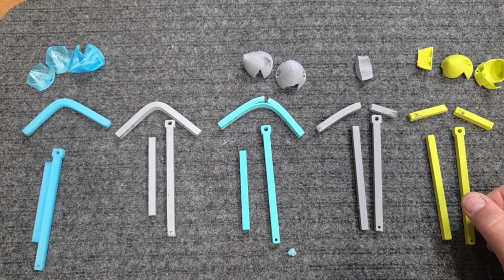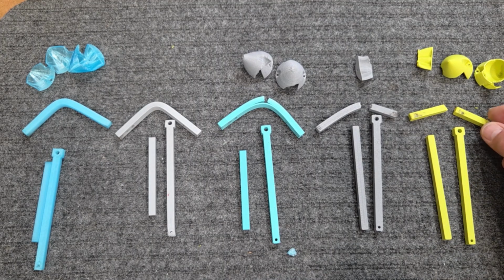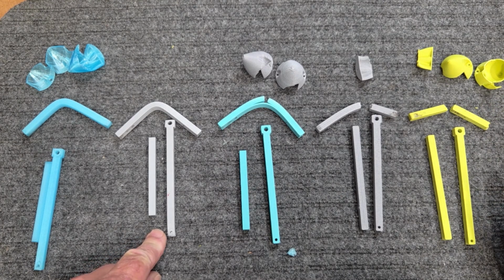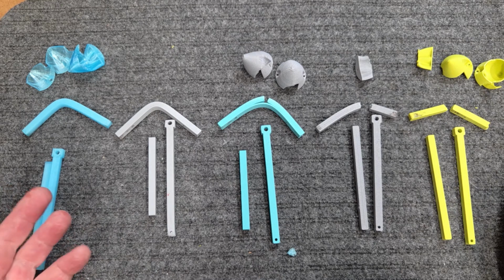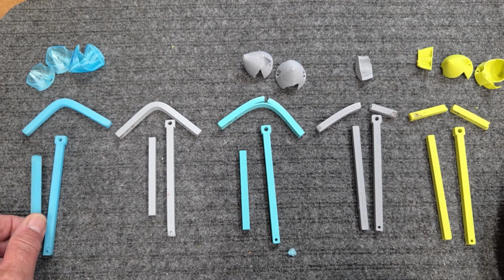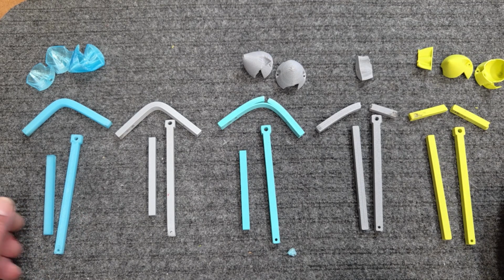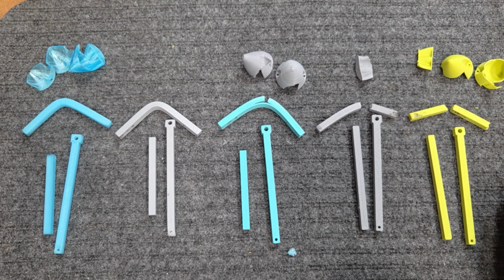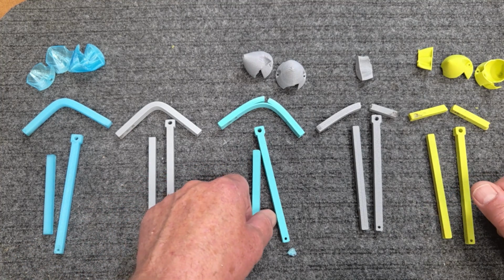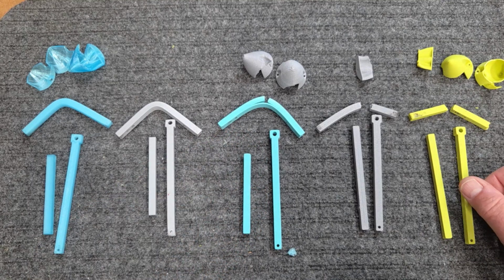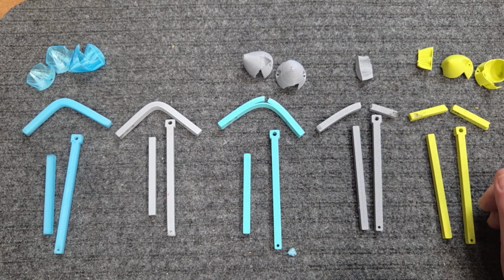Okay, so the two with the glass fibers were definitely the stiffest. They were the only two that completely broke when bending. The non-glass fiber versions were not as stiff, but they also didn't fracture. So this lends itself to the PCTG, like the specs say, being probably the most impact resistant. However, for stiffness and toughness, I think the PETG with the glass fiber is sort of the winner. Other than if you need the last little bit of high temperature, the new PLA-HT does have, rather than 70 C, I think these are up to maybe 90 to 100 C, and if you anneal them, even more. So that might be an option.